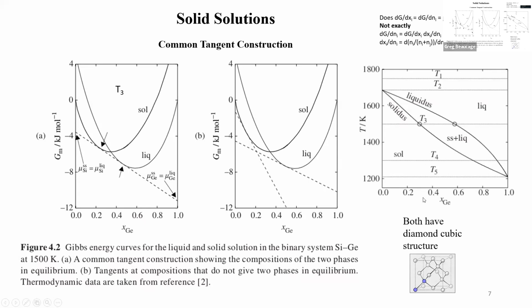Right, but if I'm right at this composition like 32, then I'm right at this spot. If you take the slope of the free energy versus composition, that's chemical potential, more or less. And the chemical potential of this one and this one are equal to each other at that composition. And in between these two, those two things continue to have the same chemical potential. So that means that if I put in this 35, it's going to separate into that phase and that phase. Right, so that's where I'm in between these two things, and that circle are these two points on the free energy plot. So you have still this simple free energy, you just have one for each of the phases that you're looking at. So basically you can construct this kind of simple liquid solid.